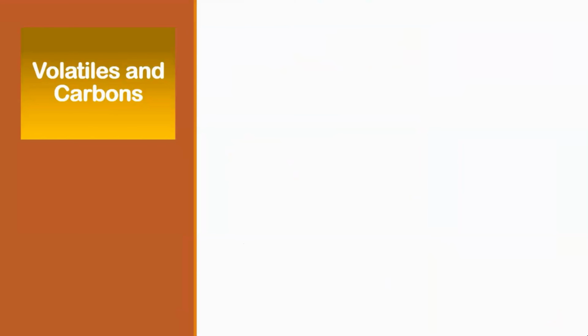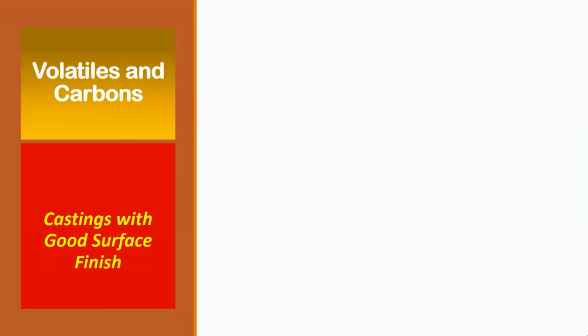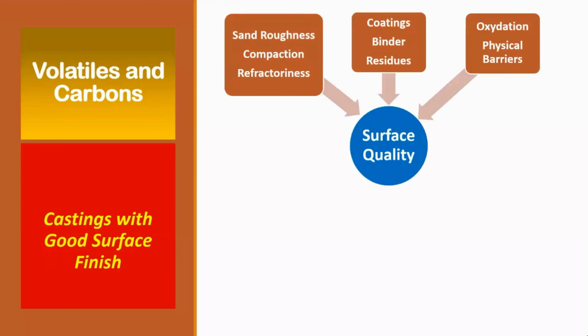Now we come to the volatiles and the carbons, which means they are going to determine how good the castings are going to look, how good is the surface finish. These volatiles are supposed to provide a barrier by creating volatiles in between the hot metal that is coming in and the mold. So it's the protective layer it is supposed to work as. So that is the purpose. The second thing is, because they are hydrocarbons, they are supposed to burn by using the oxygen in that mold atmosphere inside. So the oxygen doesn't have time to mix with the iron and then produce oxides or slag, which are again inclusions. And second, it is going to give a film. That's the general theory. We will see about it again.